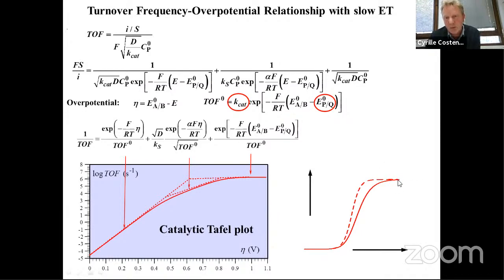Okay? And so in such a case, the only way to get rid of this problem is to reach the plateau current, where you get an overpotential which is large enough so that there is no more influence of the electron transfer kinetics between the catalyst and the electrode. Okay, then you can recover kinetic information from the catalyst, from the plateau. It's also true at very small overpotential, as you can see here or here. But in that case, you have a very small current, and so it's very difficult to extract kinetic information.